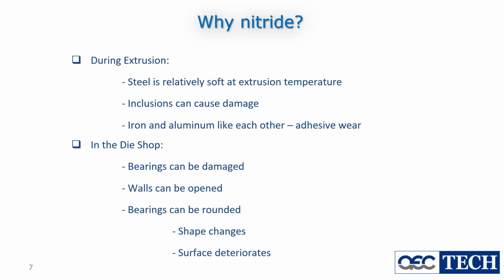Why do we want nitriding? Well, during extrusion, steel is relatively soft. H13 is particularly good at retaining its strength at high temperatures, which is why it's called a hot working steel, but it still is relatively soft compared to a hardened steel at room temperature. Inclusions in or around the billet, pieces of dirt that got onto the container with the billet, come through and can scratch the bearing and cause damage.